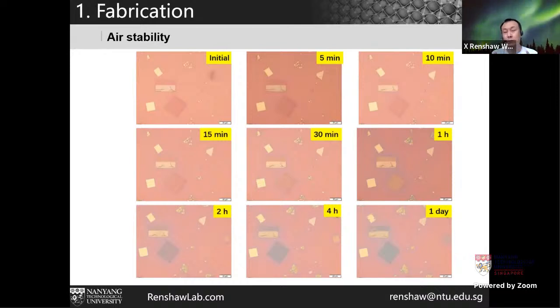Because, for example, if the material just degraded or oxidized within a few seconds, then basically we're studying, for example, iron oxide, right? And also if it's quite sensitive, we need to figure out a proper technique to protect the devices. So this is the result to test the stability of the material.